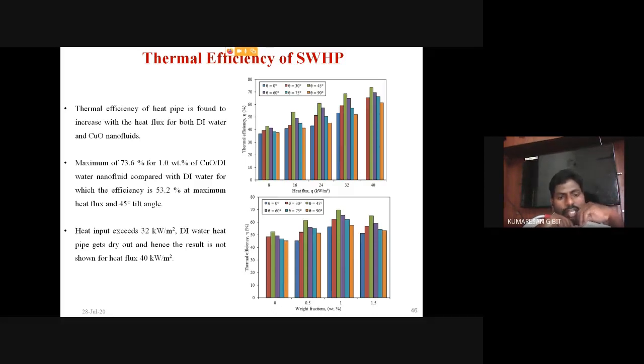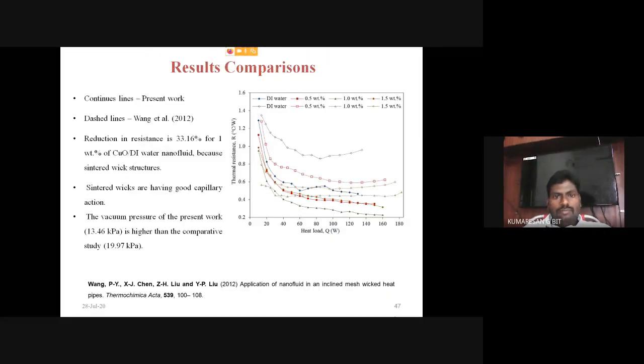Then when the heat input exceeds 32 kilowatt per meter square, the DI water heat pipe gets dry out, and hence the result is not shown for the heat flux of 40 kilowatt per meter square. Okay, so you see in the second figure, there is no blue line indicated at 0 weight percentage, because the DI water heat pipe operating at 40 kilowatt per meter square heat flux may lead to dry out conditions. So that's why the heat pipe is not operating in that particular situation.